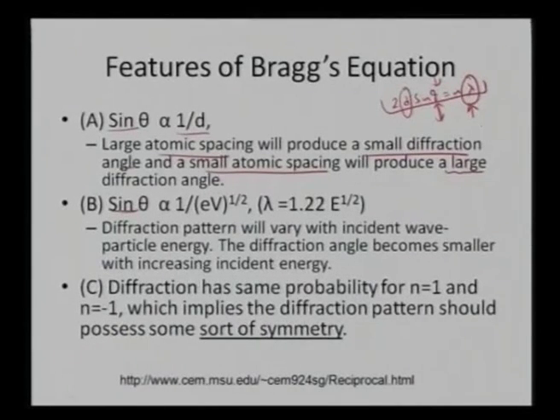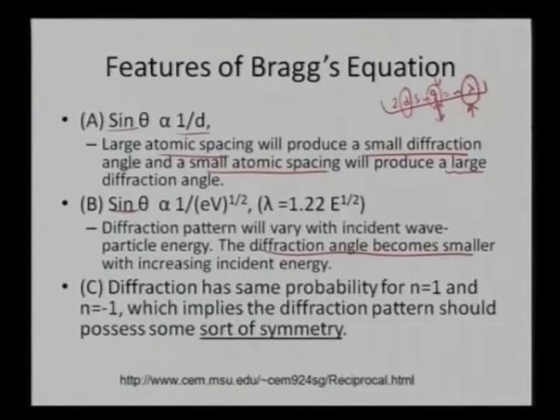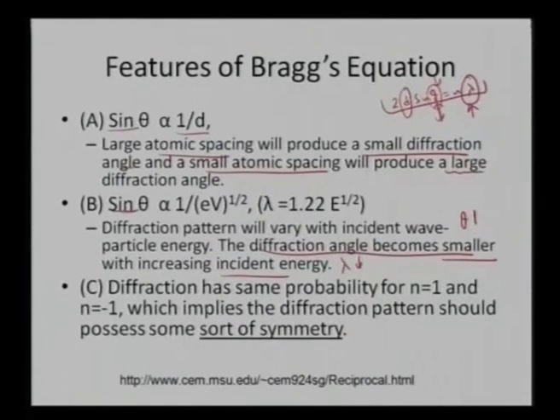For higher energy terms, I can see diffraction at much closer points — θ is very low when I have very high energy. The diffraction pattern varies with incident wave-particle energy: diffraction angles become smaller when I increase incident energy or reduce λ. My θ decreases as I decrease λ.